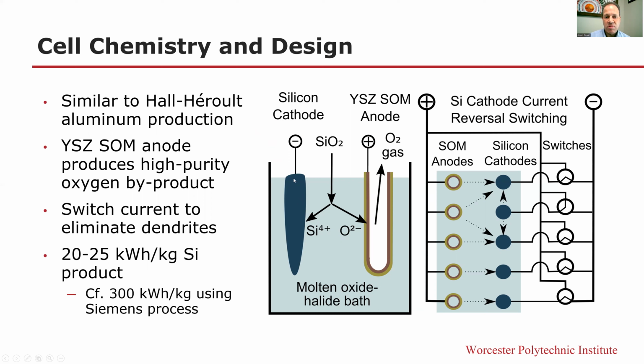But that gets reduced to silicon at the cathode, and the oxygen travels right through a yttria stabilized zirconia solid oxide membrane. This is similar to the membrane used in the fuel cell. And then an anode on the inside converts that into oxygen gas, which is a very high purity oxygen gas byproduct. So one of the challenges here is that when you grow a solid electrochemically, any roughness gets amplified very quickly into what are called dendrites.